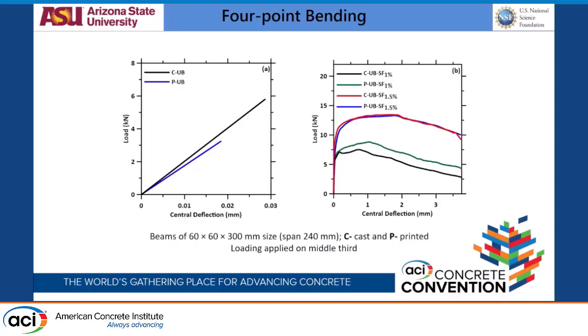But with the use of fibers, we saw a significant improvement rather than deterioration, and I'll talk about the reasoning in the next slide also. In printing, these samples are tested so that the length direction of the span of the beam is along the print direction. With the span along the print direction, the fibers are also oriented along that direction in printed samples because of the characteristic flow of these mixes. At 1%, the lower two graphs, black and green: the black is the cast sample for 1% steel fiber, while the green one is for the printed ones. There's an increase in strength in the printed sample compared to cast, because in cast you have more randomly oriented fibers, while in print you have more aligned fibers. But at 1.5% those two are more or less the same.